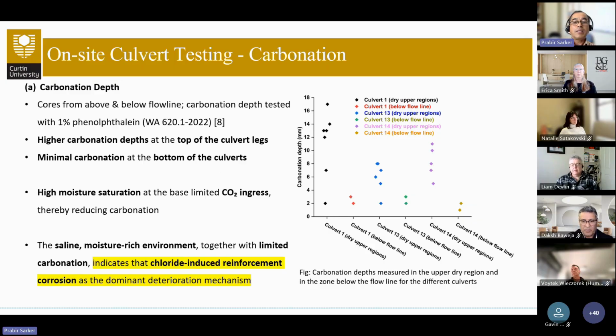Then in the detailed inspection, we went to the site to do tests for carbonation and electrical resistivity. The carbonation depth was measured on core samples, which were collected from the good areas of the legs where there was no obvious deterioration, because core samples couldn't be collected if there was already spalling or delamination.